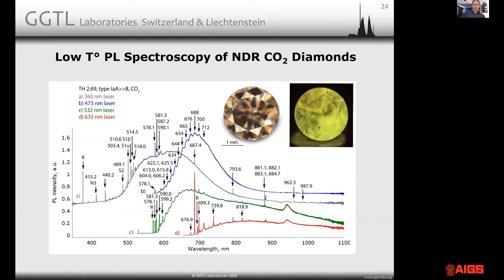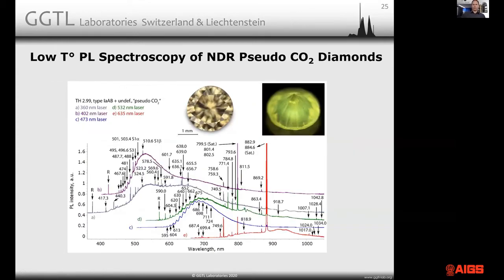Here you see a pseudo CO2 diamond as comparison. The two are virtually identical. I mean, there are obviously differences since those spectra are highly complex, but overall, they're pretty much identical. You can see in trace C at 473 nanometers, we have exactly the same 680 nanometer band as we have seen in the CO2 diamond. And note also the intense nickel band at 884 nanometers, something very common in brown diamonds, not only in synthetic diamonds.